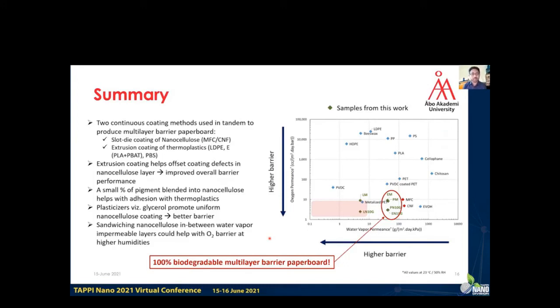Adding a small percentage of pigment into nanocellulose helps with adhesion with thermoplastics, and the small percentage also keeps the barrier properties intact. Plasticizers such as glycerol promote uniform nanocellulose coating and therefore better barrier. And finally, sandwiching nanocellulose in between water impermeable layers could help oxygen barrier at higher humidities.